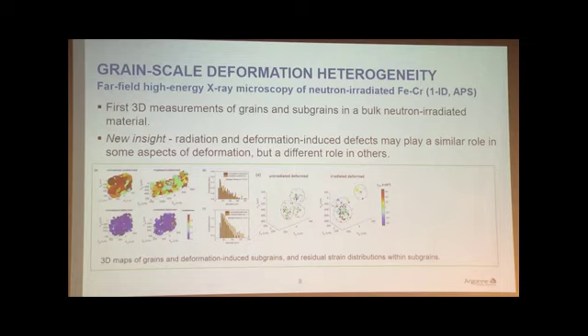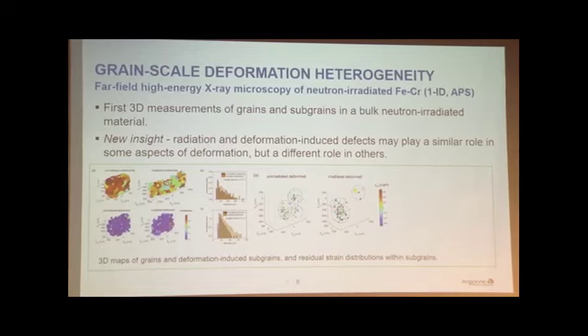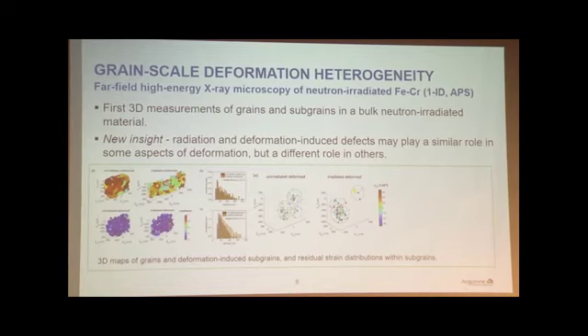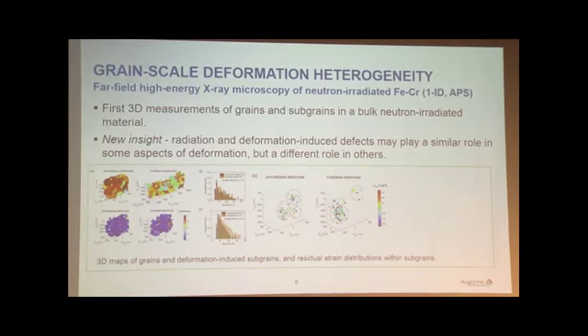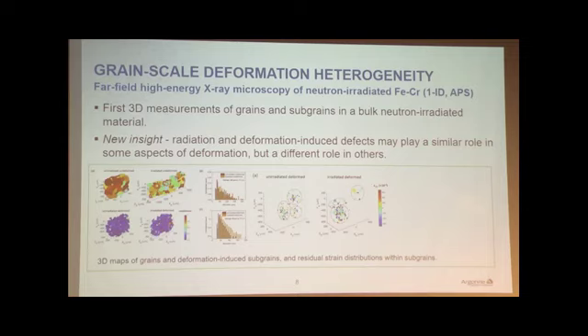This basically uses a 3D characterization technique, so-called high-energy X-ray microscopy, to look at the deformation microstructure, how the radiation affects the deformation. Because we know in our community, we often use the TEM to study radiation defects. We have a very good understanding of the defect generation. We also have a lot of mechanical testing data, so we understand the property. But it's very difficult to put these two pieces of information together because we really don't have a lot of information at the intermediate scale. So this high-energy microscopy technique now allows us to look at individual grains or subgrains.